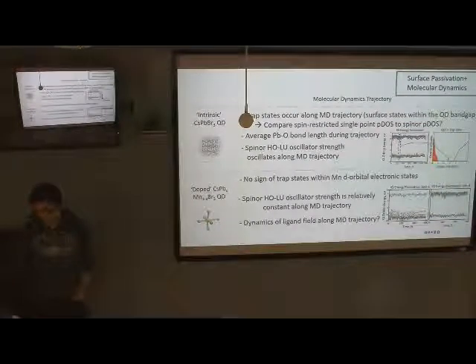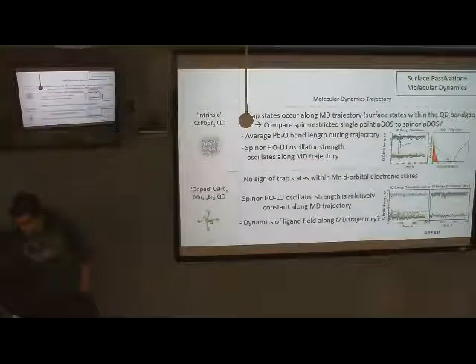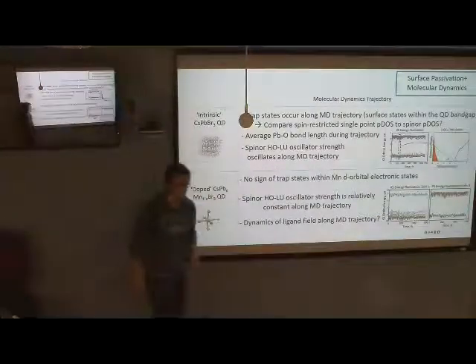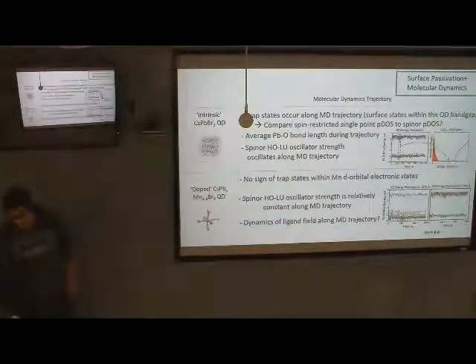So that's the intrinsic dot, and with the doped system it's not as interesting. We did spin polarized, so we have two different energy fluctuations. You have your spin alpha, where all the up spin states are from the manganese, and these two states here that are separate from everything else are d states, or dehybridized. So they're from the manganese. You can see that along the trajectory, there are no states that pop up in between them, so surface states don't affect there. And then spin beta, that's where all the unoccupied d states are, where the transitions would come from.